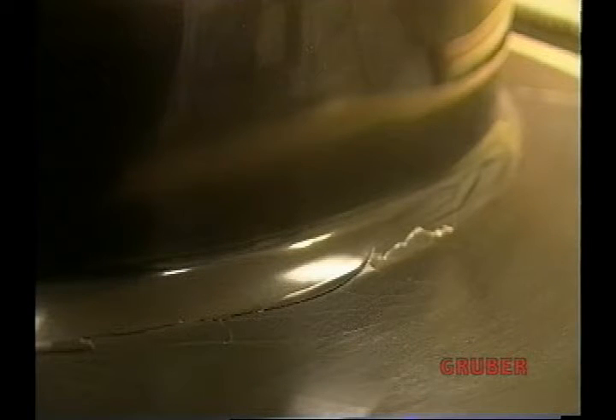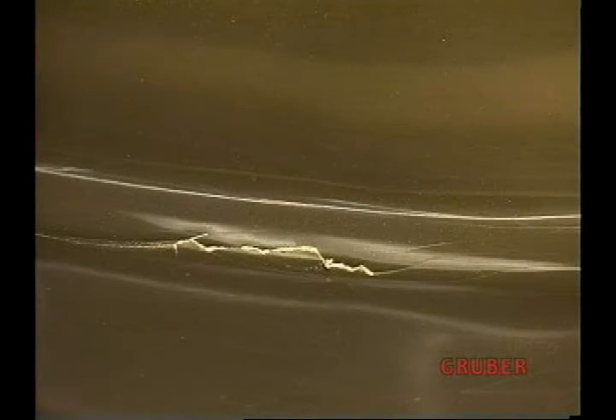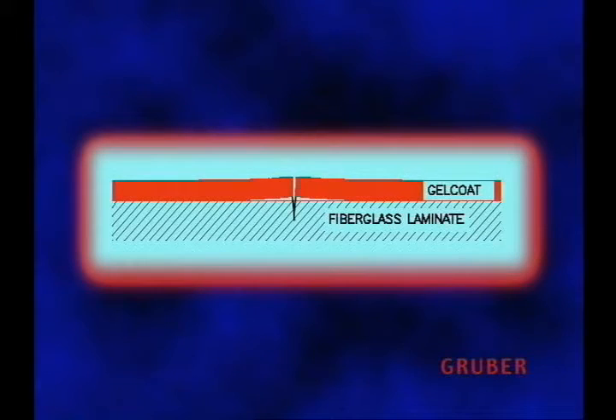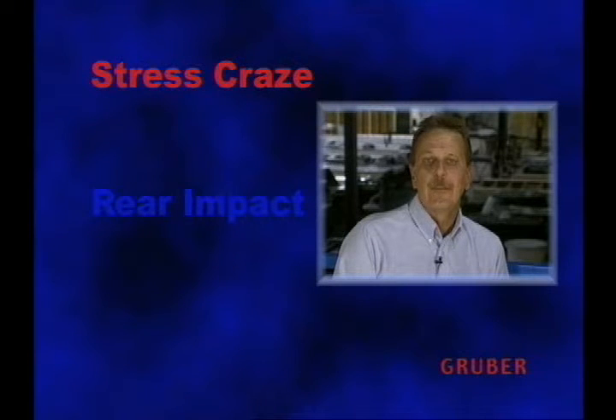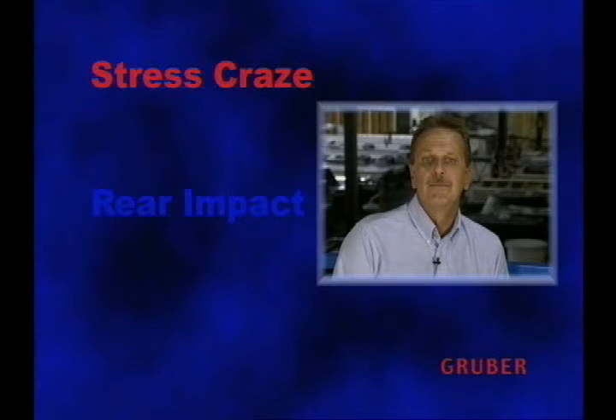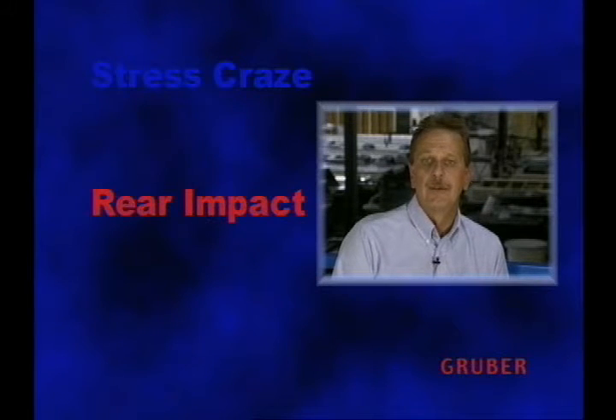Although the most severe cases of stress craze are in fact repairable, it is generally cost prohibitive to do so. This graphic illustrates that the stress craze extends through the gel coat into the laminate. Stress craze occurs when a mold is bent beyond the breaking point of the gel coat — most often this happens on bowls, but can also affect larger molds like tubs.